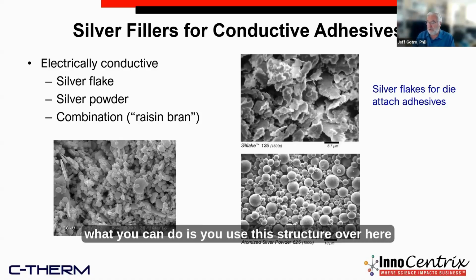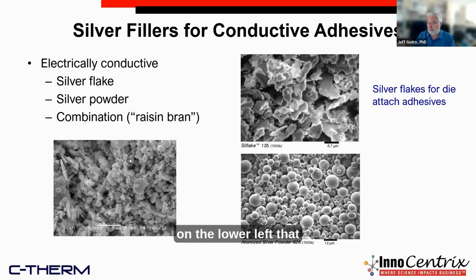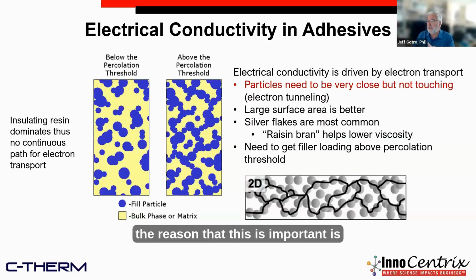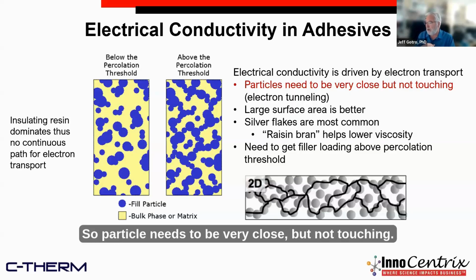So what you can do is you use this structure over here on the lower left that has a combination of these silver flakes and spheres, hence my term raisin bran. And the reason that this is important is because if you have not enough filler in there, so this cartoon on the left, too much yellow, which is the bulk matrix, you don't have a pathway. So then you need to get to the percolation threshold, as shown in the right-hand side of this cartoon. And now you have a path from one interface to the other interface. But in order to get electrical conductivity, you have to have electron transport. So particles need to be very close but not touching.